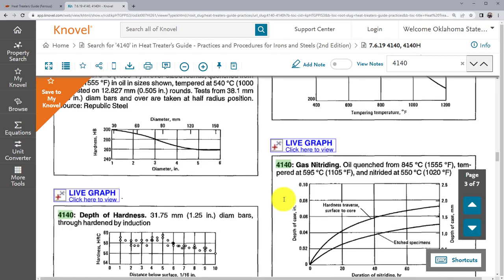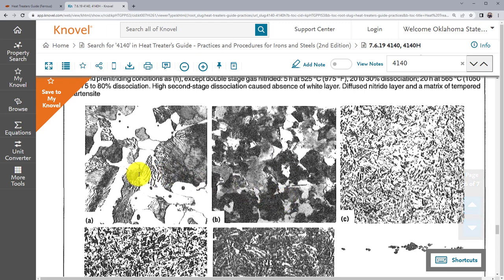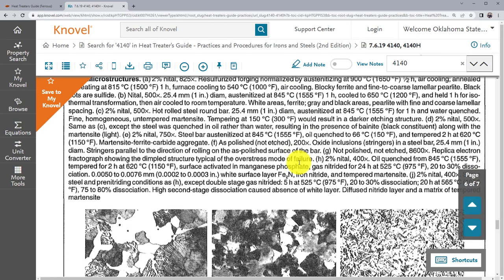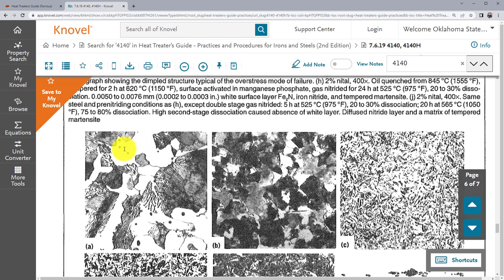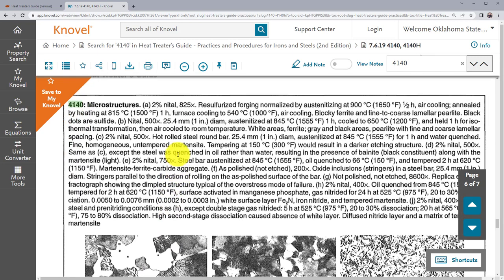In future labs, we're going to learn a lot of stuff in here and you're going to need to data mine some of this for various things. And looky here — we have sample microstructures for that material. Let's look at A right here. What did we do to A here? We basically normalized this — a better grade of annealing if you want to think about it. We basically annealed this sample for an hour, and it tells us what we see: ferrite and coarse pearlite. We're seeing these nice ferritic grain structures with the fingerprint-looking pearlites in here. So we can kind of sense what an annealed 4140 is going to look like. In the lab, we're going to hand you some annealed samples and you're going to be able to compare and identify those structures.